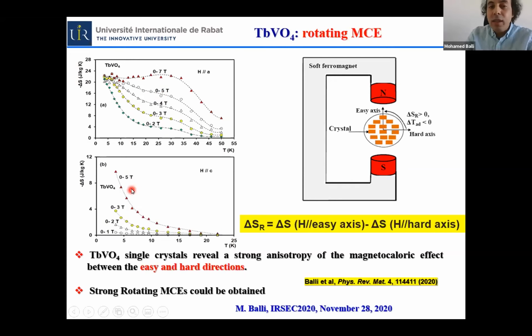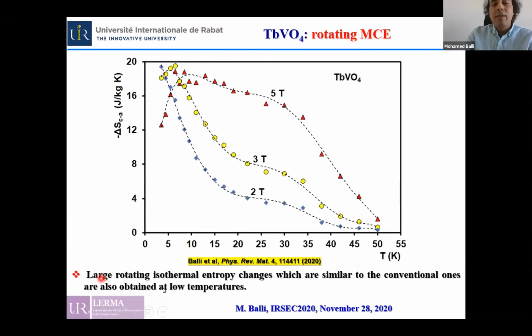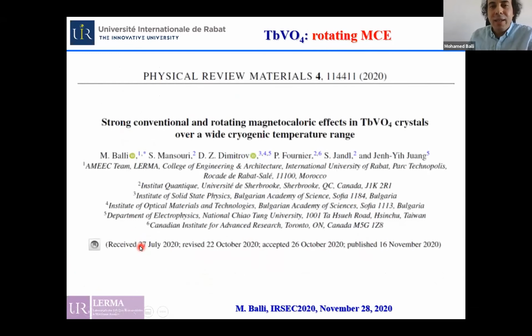Accordingly, the materials also involve a large rotating magnetocaloric effect similar to the conventional one. This rotating magnetocaloric effect, as shown here, can cover a wide temperature range, going from 50 to 0 Kelvin. For more information about how the crystalline field acts on the magnetic and magnetocaloric properties of the terbium vanadate compound, please take a look at this very interesting paper just published a few days ago in Physical Review Materials.